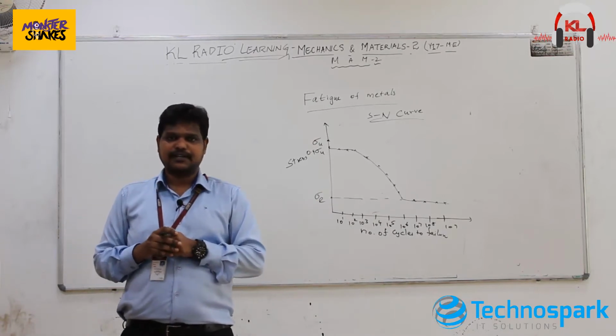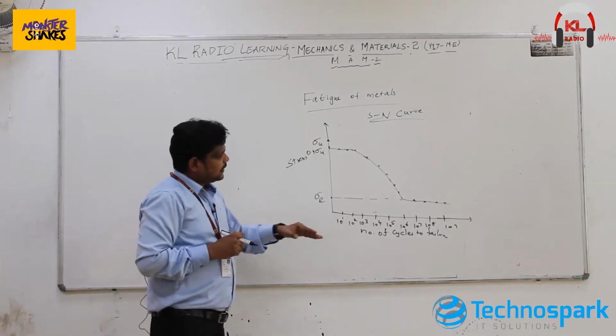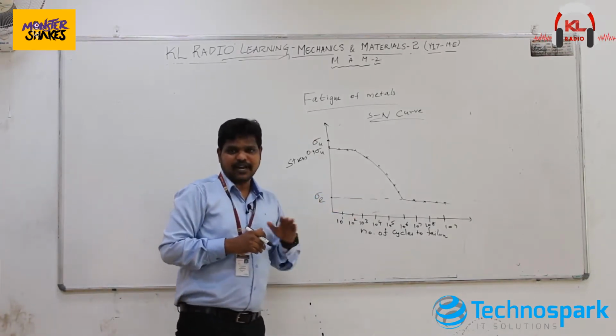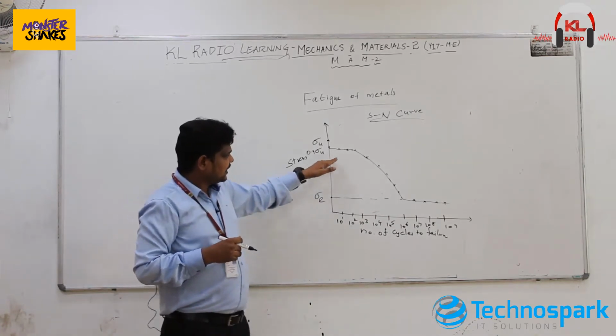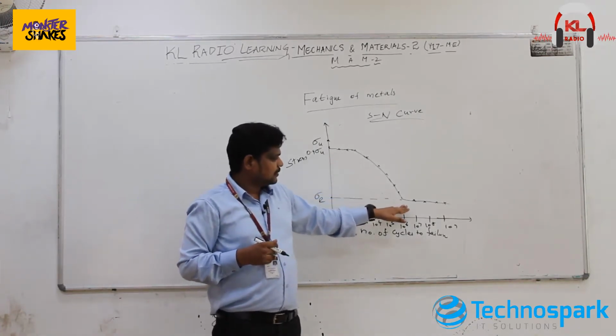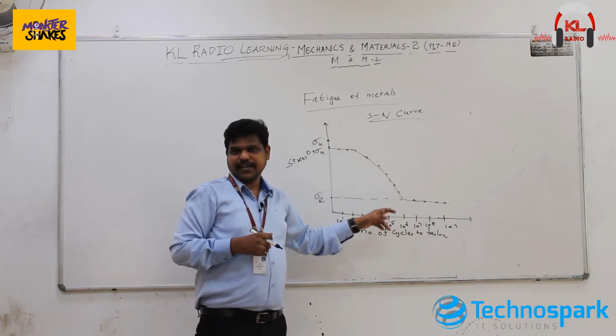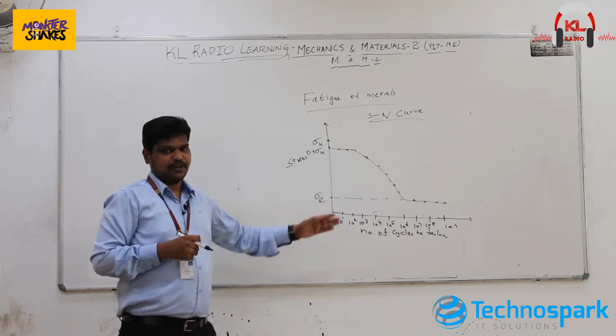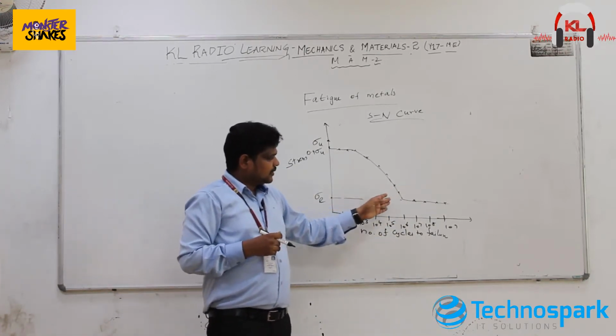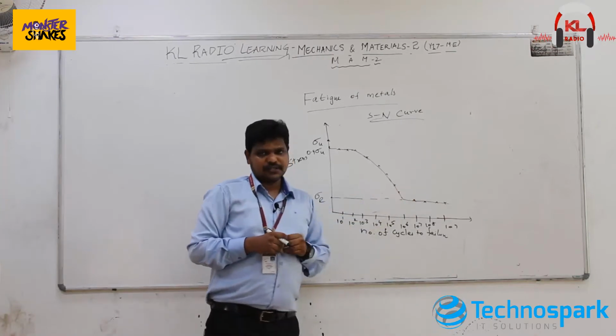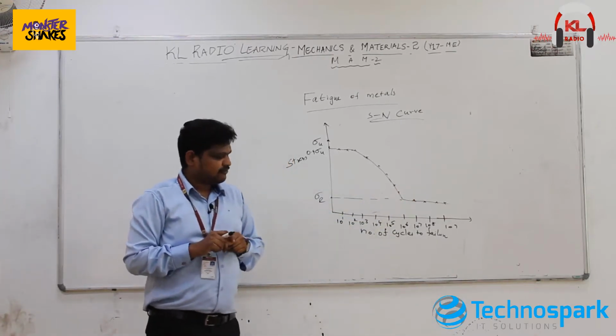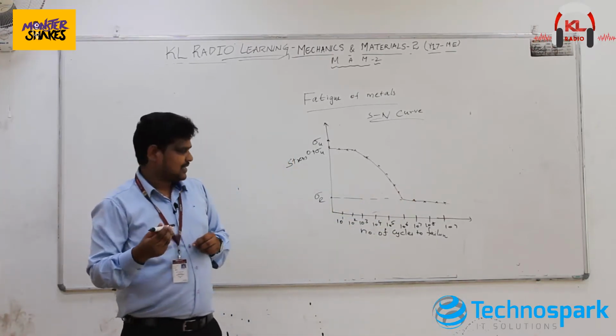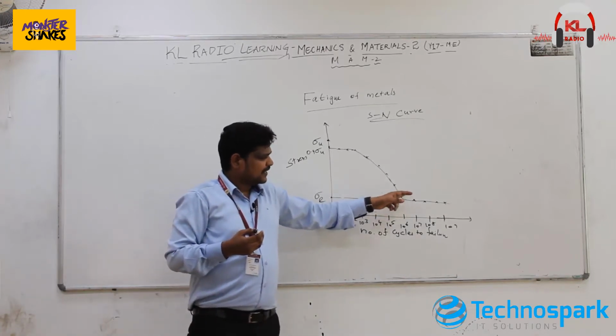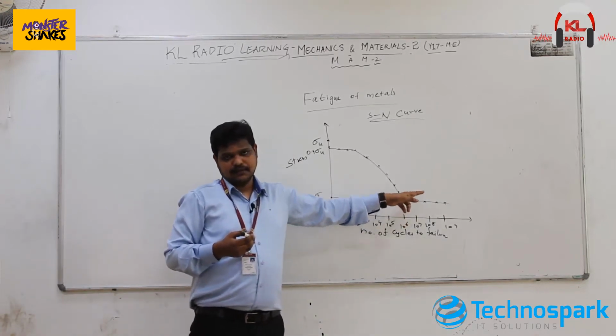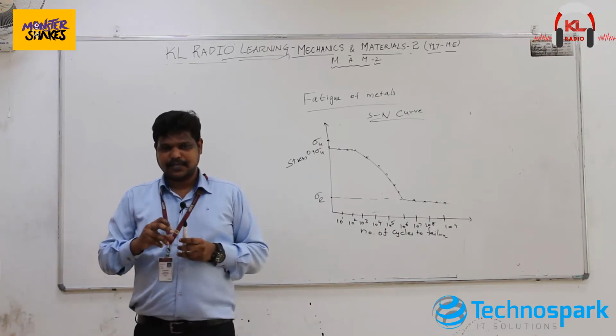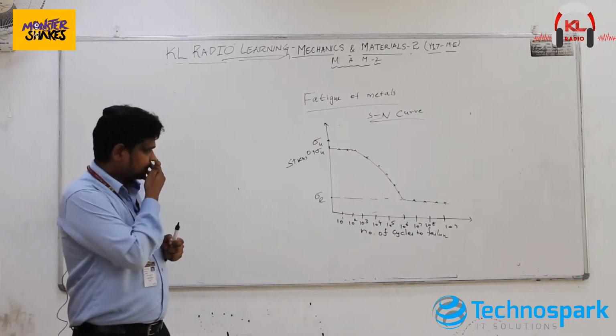So those factors have to be considered when you are choosing the endurance limit for designing a component which is subjected to fatigue conditions. And one more thing has to be noticed: for aluminum there will not be a pattern in this fashion, so it will not have a well defined endurance limit. So we usually choose the stress limit at 5 into 10 power 8 cycles as the endurance strength, near that 10 power 8 cycles, to design a component made of aluminum. Right.